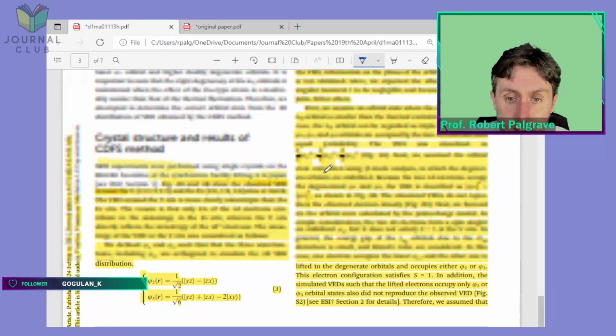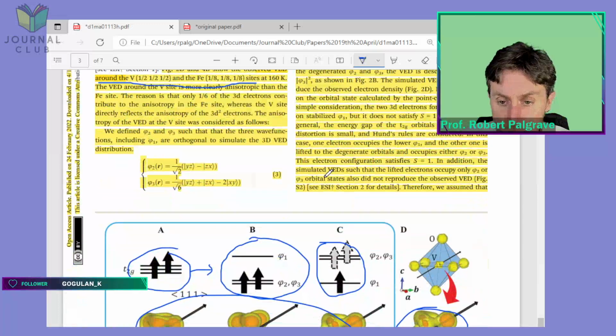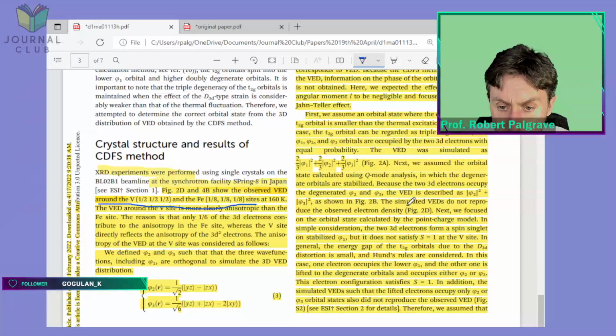Let's let them say that in their own words, because I'm sure they say it in a nicer way than I did. Okay, the simulated valence electron density does not reproduce the observed electron density, figure 2d. Next we focus on the orbital state calculated by the point charge model. In a simple consideration, the two 3d electrons form a spin singlet on a stabilized Psi1, but it does not satisfy S = 1 at the V site. In general, the energy gap of the t2g orbital due to the trigonal distortion, due to that Jahn-Teller distortion, is small and Hund's rules are considered.